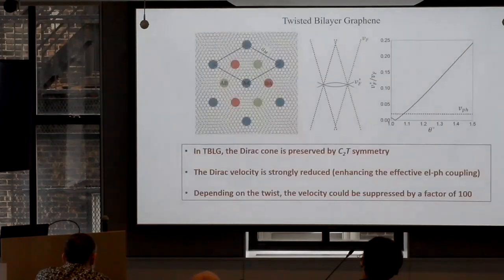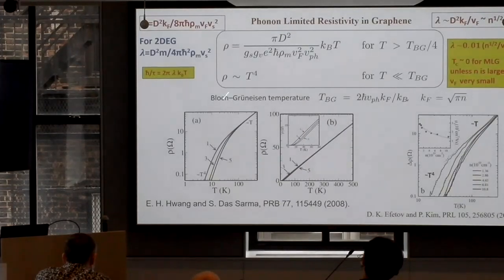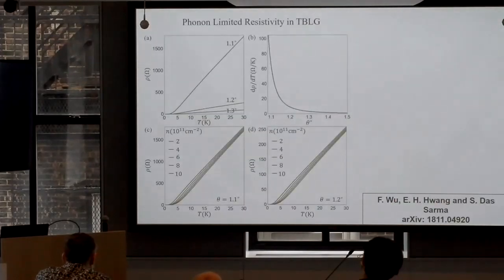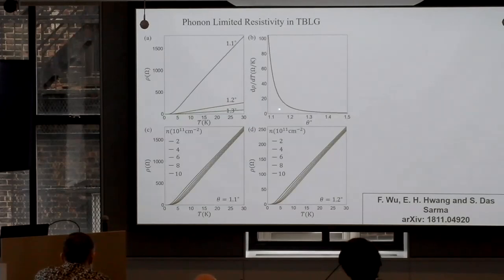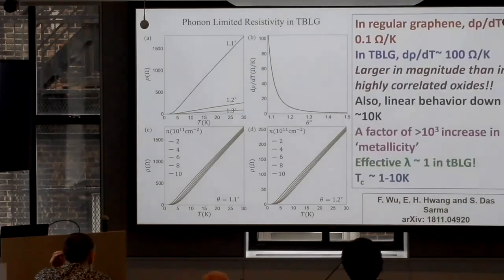And I could just immediately get resistivity as a function of twist angle. All that is coming in is this. This is basically this formula recycled, doing the full calculation in between, recycled now with the Bistritzer-MacDonald band structure for graphene velocity. So as you can see on this plot, the monolayer graphene will be basically along the horizontal axis. And as the angle goes down, resistivity should go up enormously, okay? And d rho dT should show this huge change, 100 to all the way 0.1 ohm per Kelvin, as you go from small twist angle, let's say 1.1 degrees, at magic angle in our theory diverges, to regular graphene, okay? And this agreed remarkably with the experiment.